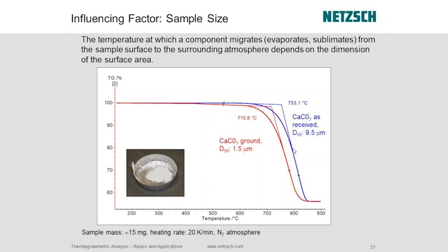But here you're looking at particles. 10 micron particles versus 1.5 micron particles. And if you think about this, it's intuitively obvious, I suppose, that the finer the particle, the more exposed it is to the atmosphere, and the freer it is to liberate the gases that want to come off. So as we say here, the temperature at which the component migrates from the sample, so the gas that's evolved from the sample, whether it evaporates or sublimates from the sample surface to the surrounding atmosphere, depends on the dimension of the surface area. So the higher the surface area, usually you're going to see a better evolution of the gas species. So that's basically what we see here, right? We look at this 1.5 micron powder, and you can see it begins to lose mass at a temperature earlier than what we have with the larger particles.